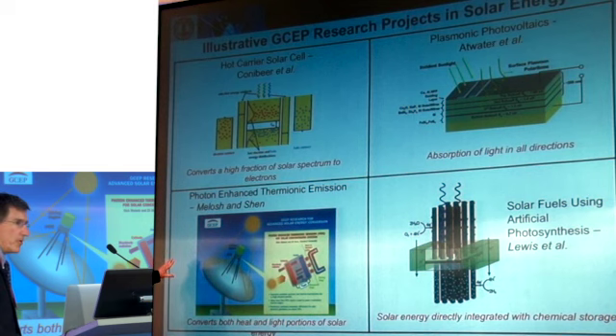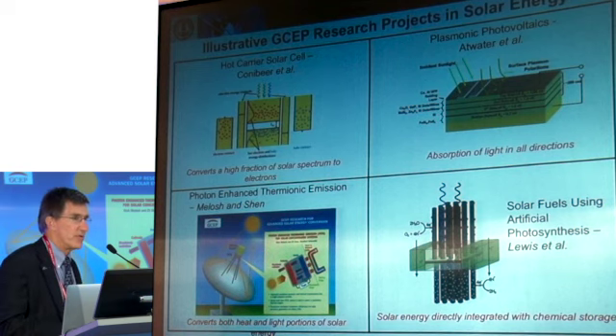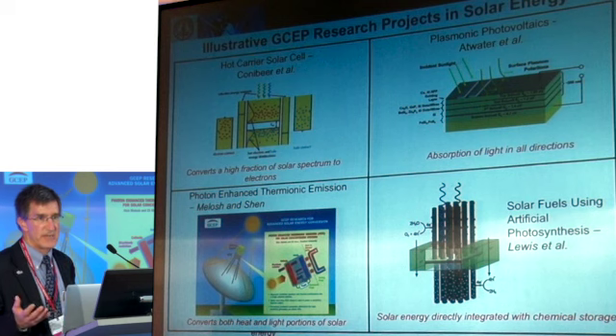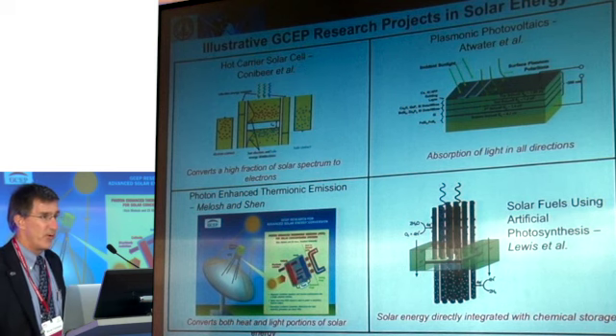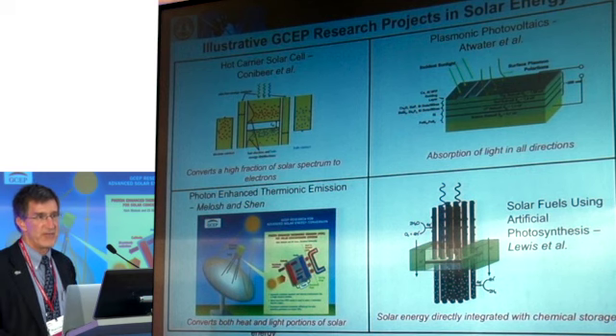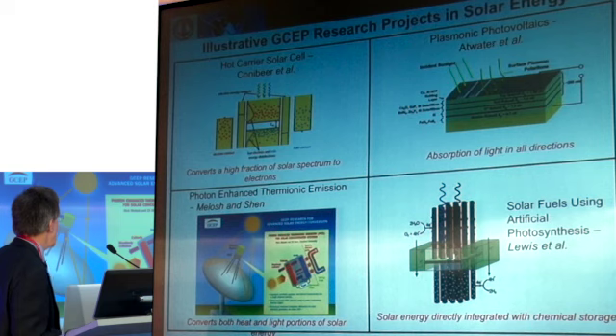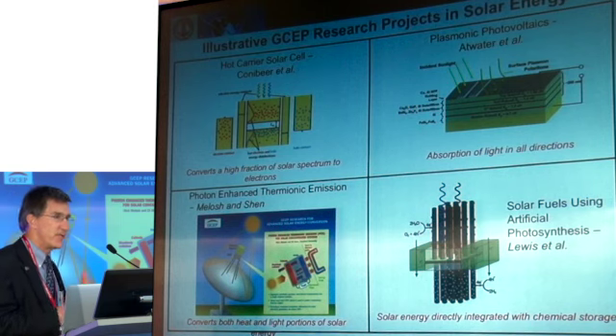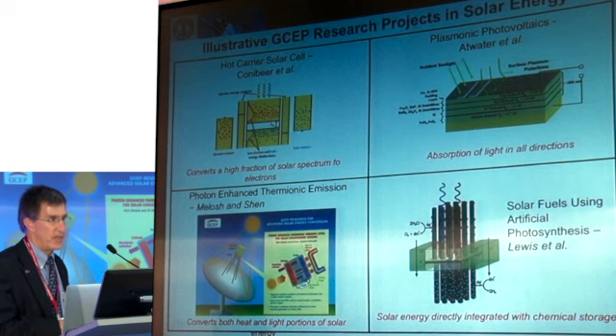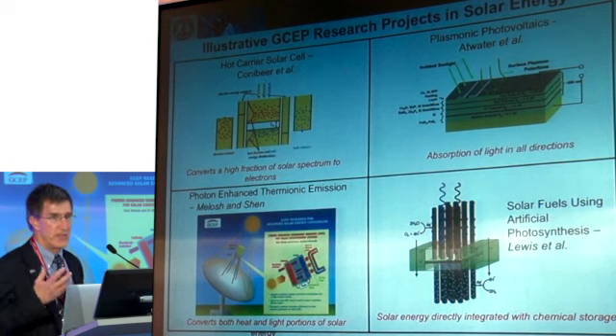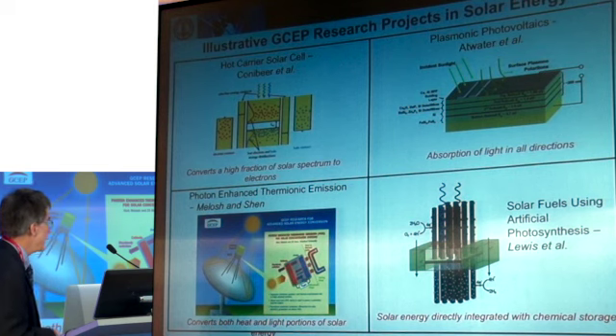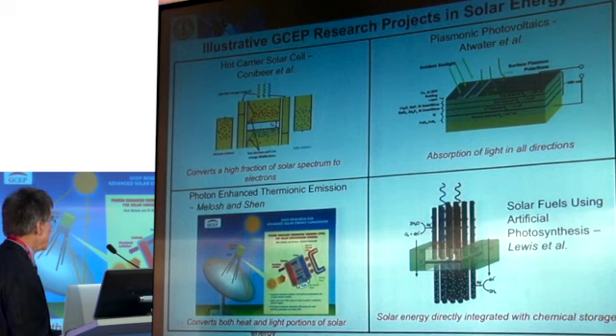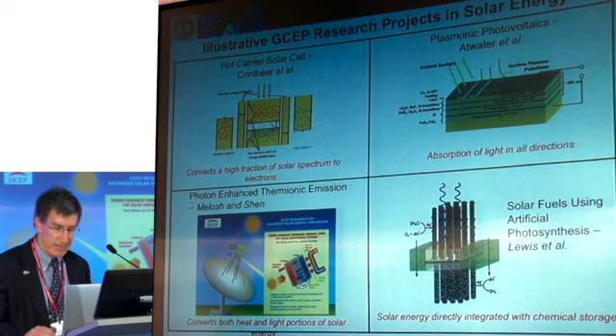This is a completely new approach that's based on photon-enhanced thermionic emission. So this is a solar cell that works better when it gets hot. One of the sad things about solar cells is you put them out in the sun and they warm up, and when they warm up, they work worse. The efficiency drops when they get hotter. But with this photon-enhanced approach, it works better when it gets hotter. So this could be combined with a thermal energy capture system in order to increase the efficiency of the whole system. And then she also mentioned this work on solar fuels where they're looking at making both anodes and cathodes with a very clever nanostructure or microstructure approach to material fabrication.